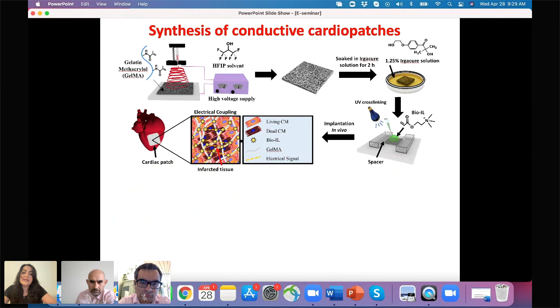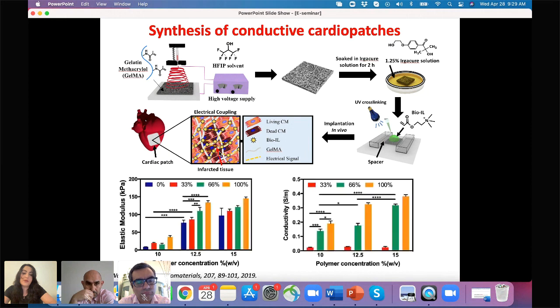So the way that we synthesize these cardiac patches, we use a biopolymer. In this example, we use gelatin methacryloyl, or GelMA. We use electrospinning to form a fibrous patch based on GelMA. And then once we form this patch, we soak them in Irgacure solution. It's a photoinitiator. And then by adding bio-ionic liquid, and after photocross-linking, we form these electroconductive patches with tunable properties.